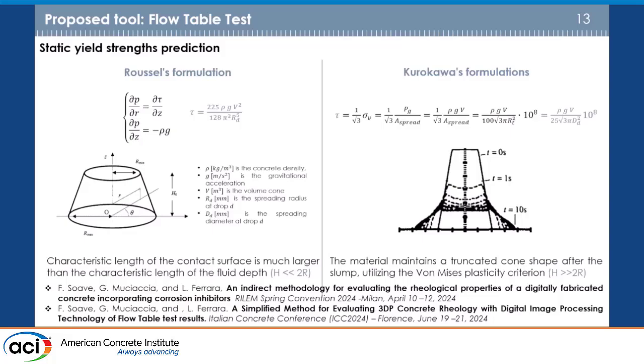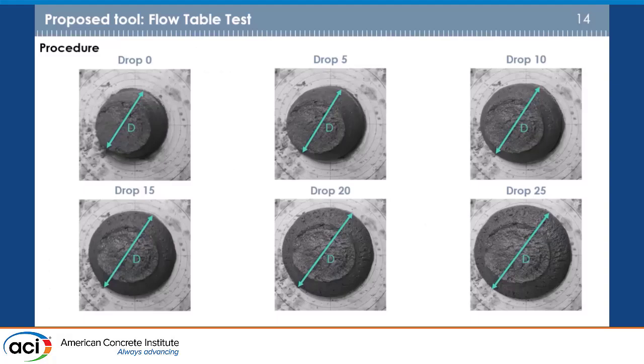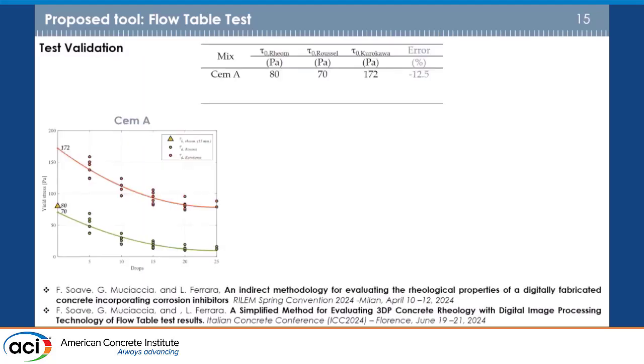What is the difference between the 2 formulations? One, as I said, works very well for SCC, a material with relatively low yield stress, because it's based on the fact that your truncated cone shape converts into a flowing patty, completely flat. The other one works for medium to high yield stress concrete because it's based on a combined shape. There is a part which flows and another part which remains in the form of a truncated cone. We also used some digital image recognition: we took movies of the flowing patty, identified the geometry, fed it in, and validated the approaches.